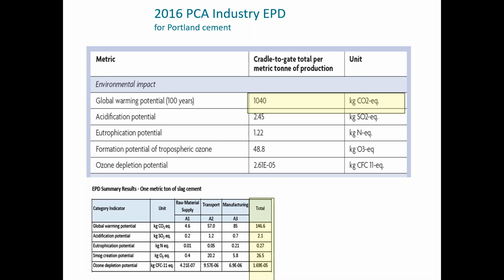This is an example of the Portland cement industry EPD. If we look at the top there, we see the global warming potential for cement, and we see that it's just over 1,000 kgs. If we look at that industry EPD for slag, we see we were at 146. So as we are looking into the concrete end, we are supplementing slag cement in replacement for the Portland cement, which we can see is going to lower, per ton, the amount of CO2 as well as the other environmental impacts. Next slide.